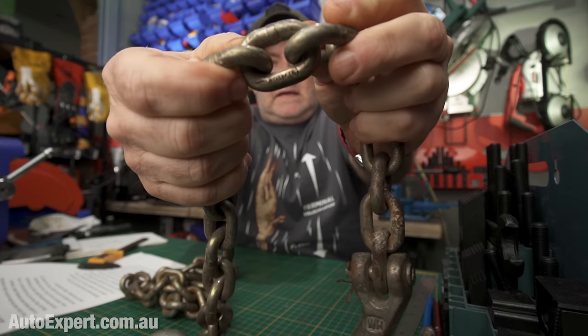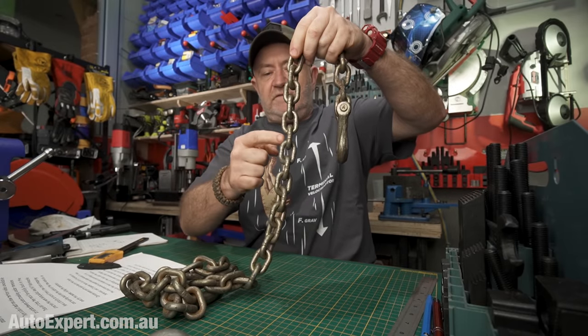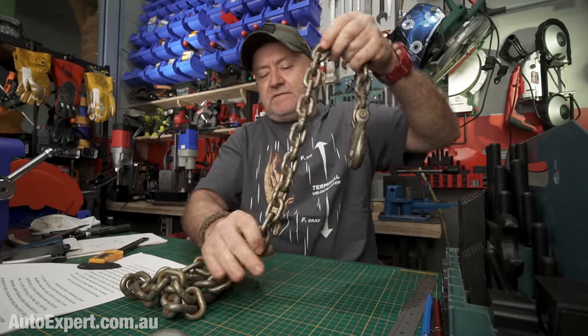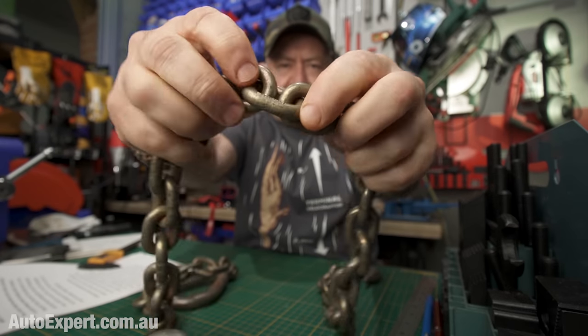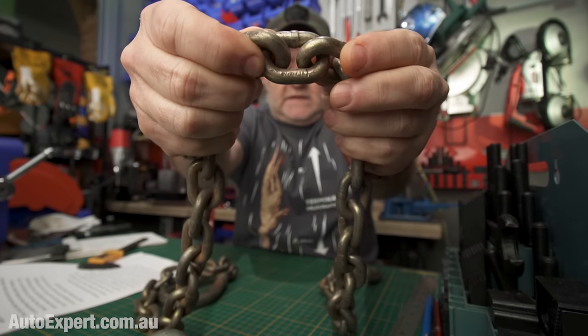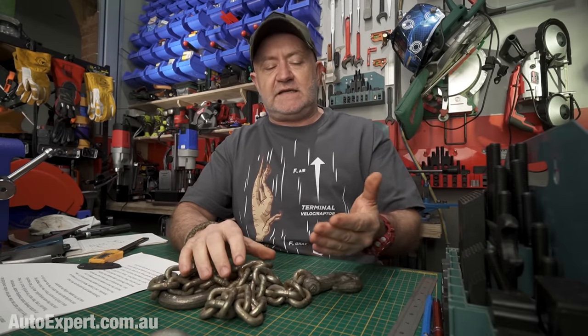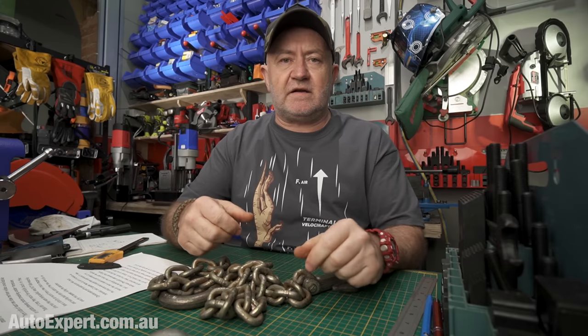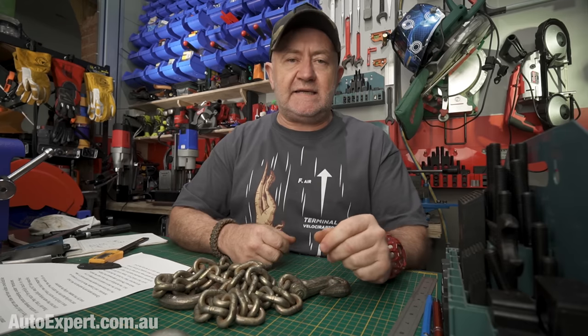It's eight millimetre chain, nothing to do with the dimensionality of the links. Every 12 links there are stampings — that's how you know this is the standardised stuff. AS/NZS 4344 compliant chain. The purpose of standardising it is that it's all uniform and we know how it's going to behave. The problem lies in going out in the field for four-wheel drive recovery, because unlike being in a factory, you don't really know what loads you're imposing. But this stuff has a lashing capacity of 3.8 tonnes and a minimum breaking strain of about 8 tonnes — a two-and-a-bit factor of safety.